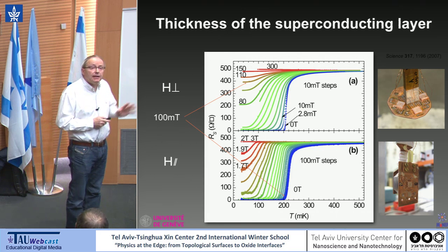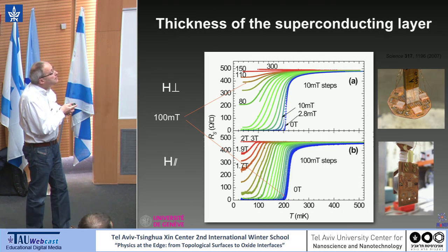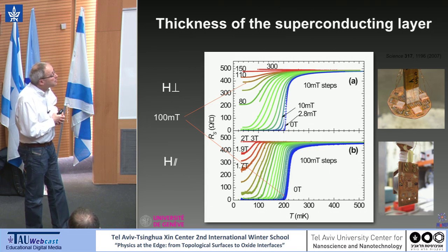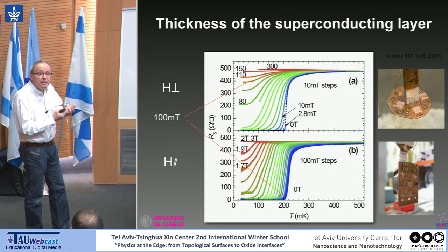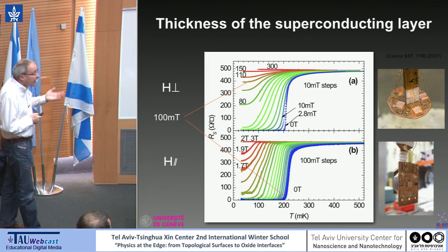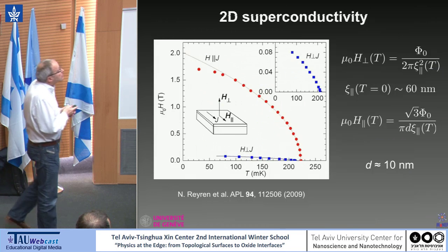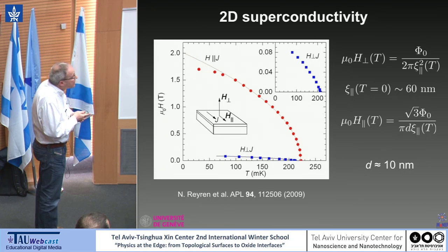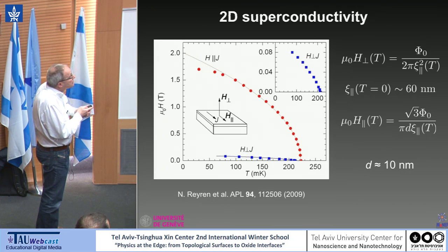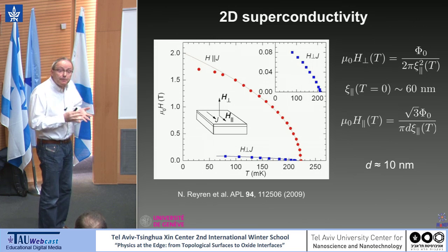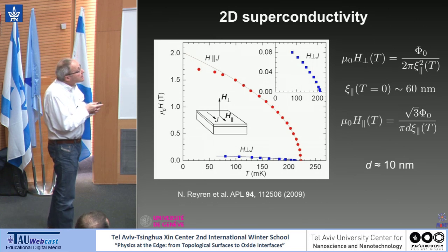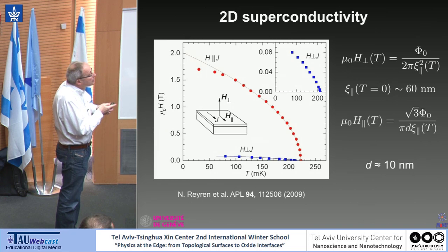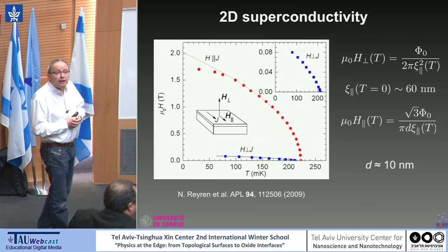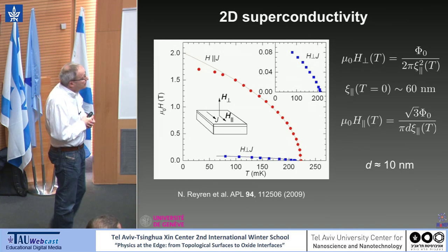Now, if you have this data, you can determine TC by choosing a criterion, for instance, 50%. You take the temperature at which the resistance drops by 50%, and this is giving you the TC for a given magnetic field. And now with this data, you can trace the critical field. So this is critical field versus temperature. This is the perpendicular direction and the parallel direction. For the perpendicular direction, you can extract, using this formula, the in-plane superconducting coherence length, which is maybe 60 nanometer or 70 nanometer, depending on the sample.